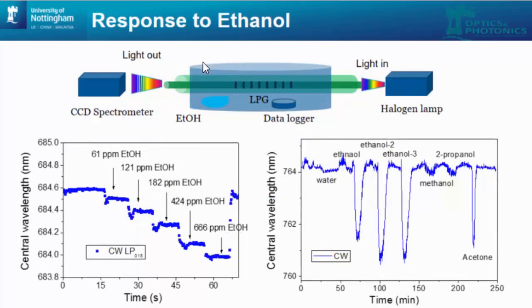So after we coated the optical fiber with metal organic frameworks, we calibrated it by exposing it to ethanol. In our work, we have used ethanol as solvent, and this determines the selectivity. So we have a good selectivity to ethanol, for instance, as compared to other alcohols, such as methanol and propanol here, for example, and a very small sensitivity to water. Acetone does influence the sensor response, and it's mainly because the selectivity is size selective, so acetone is much smaller than ethanol and penetrates into these pores.